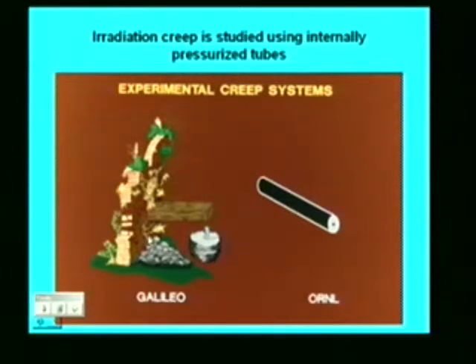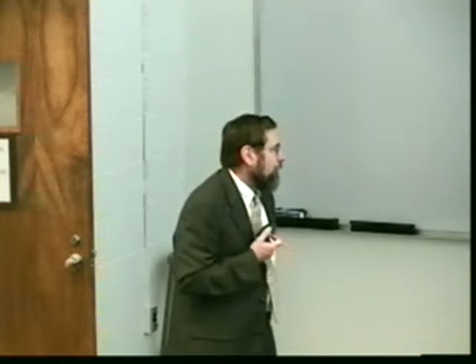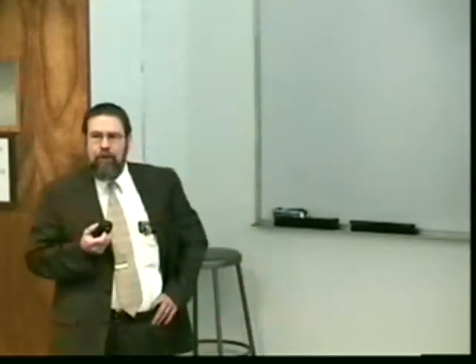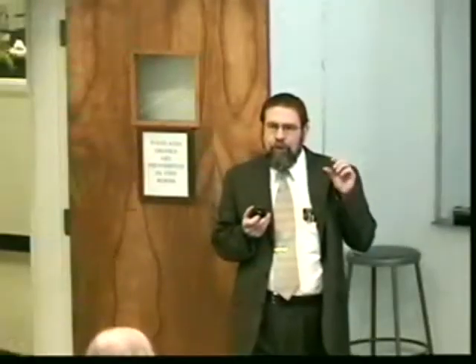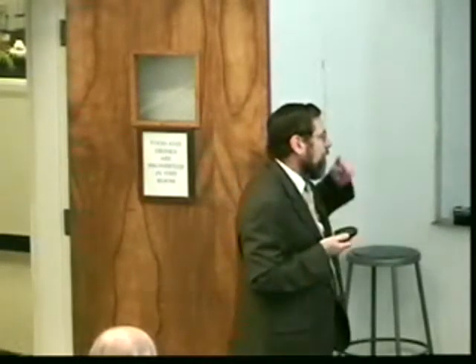We said we could just hang a weight on a wire. Well, he used a beam and then hung a weight on the beam to measure deformation. Things haven't changed too much. The principles are the same. We often use a pressurized tube. So we have a tube and we put it in a pressure bomb, pressurize it with helium to a desired level, and then shine a laser through a sapphire window and seal the tube. This is a common way because they take very little space. We can put them in a reactor and we can study quite a variety of stresses. So it's a very convenient way to study radiation creep.